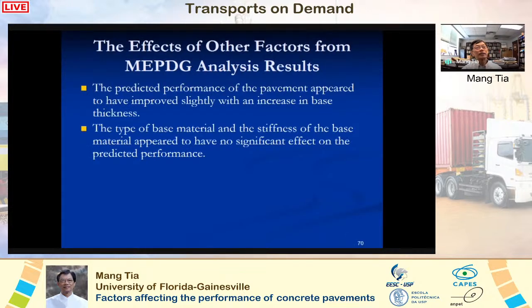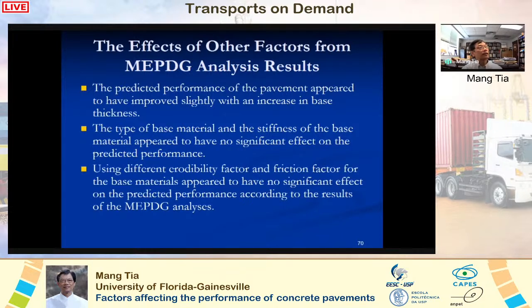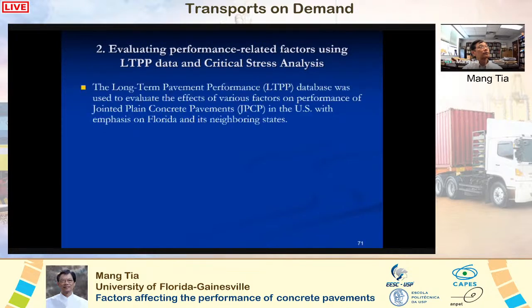Okay, and so we can make these conclusions: the predicted performance of the pavement appears to have improved slightly with an increase in base thickness. The type of base material and stiffness of the base material appear to have no significant effect on the predicted performance. And also using different erodibility factor and friction factor for the base material appear to have no significant effect on the predicted performance according to the results of our MEPDG analysis.